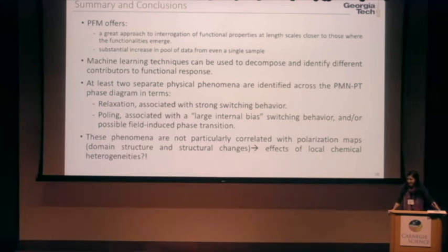I'm thinking you suggest that the different behavior in different places could be related to chemical heterogeneity. Another possibility is that you may have the same material, but something like domains, so different crystallographic orientation. Imagine a ferroelectric domain, where looking along the polarization you would expect out-of-plane piezo, and perpendicular to it you would not. So my question is, did you ever think about or try to compare or look in the literature at how it would be in thin films, where, for example, I would have some kind of texture?